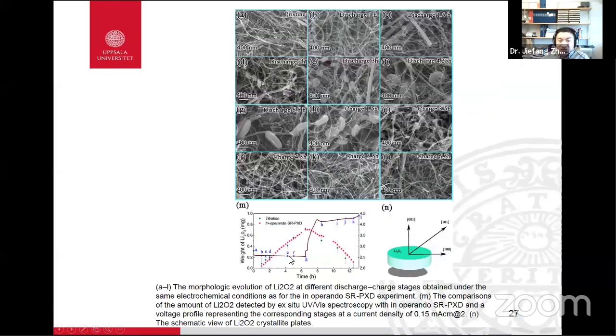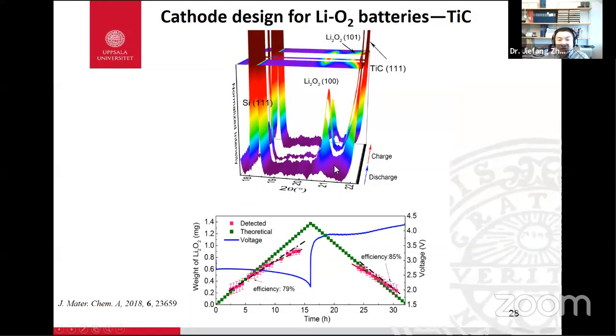This was confirmed by the SEM observation at different stages. For example, at the very beginning we see the disk, then we see the toroid structure, but then the toroid becomes a disk again and decomposes. So this is the SEM observation. And also, we use the new design cell for new catalyst research, for titanium carbide used in the lithium oxygen battery. This is for the discharge stage. This is for the charge stage.